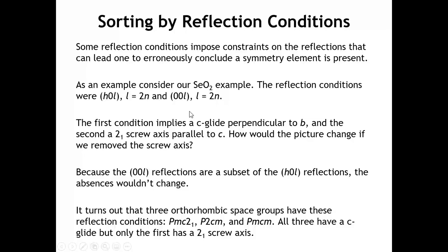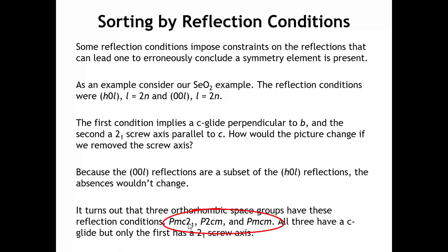How would our absences change if we removed the screw axis? The first condition wouldn't change. You might think we'd start to see all the 00L peaks — the 001, 003, 005 — however, the 00L peaks are a subset of the H0L peaks, and for the H0L peaks L has to be an even number. So even without a screw axis, we're still not going to see the 001 or the 003. This means there are three possible space groups with these reflection conditions: PMC 2₁ — the space group for selenium dioxide — but also P2Cm and PMCm.